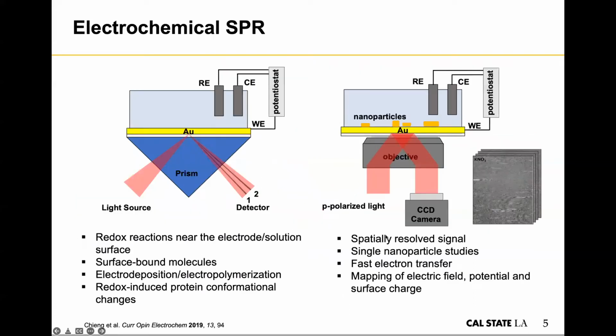And then SPR can be combined with electrochemical measurements. It has been used for a long time for traditional SPR setups with no imaging capability, as we call it electrochemical SPR or EC-SPR. In this case, you simply use the gold surface as a working electrode. The gold surface works as an SPR sensor, but at the same time it is used as the working electrode, and you have the reference and counter electrodes inserted. So there will be an electrochemical cell built on top of the SPR detector, and this has been used for different applications as listed here.